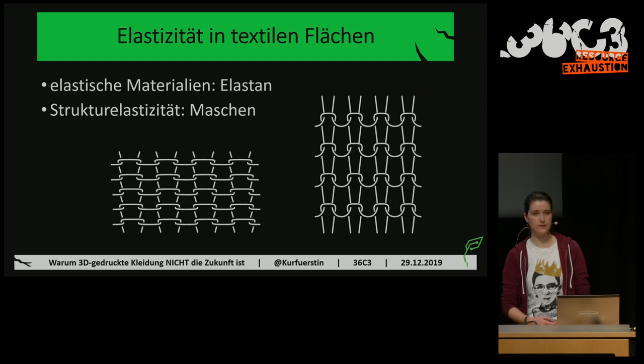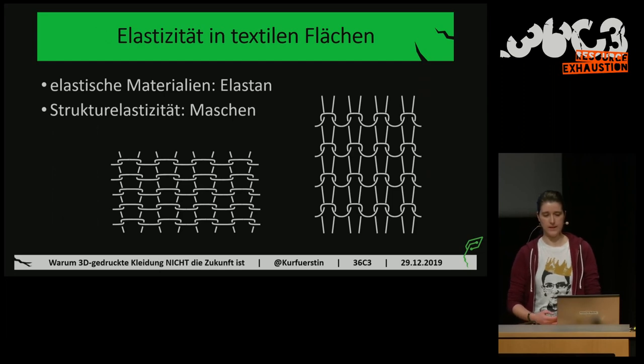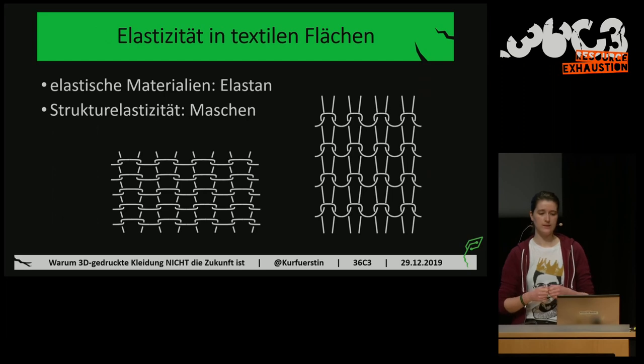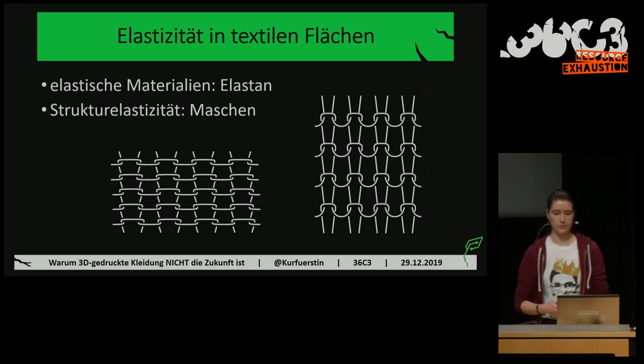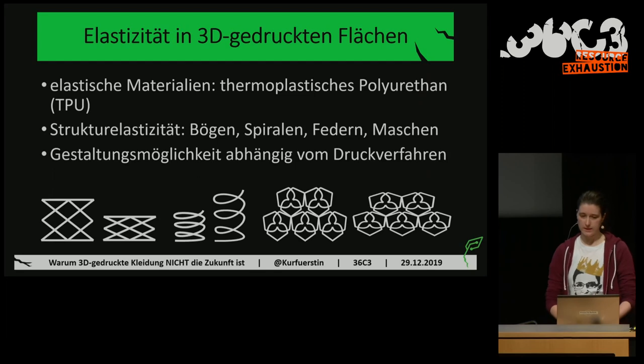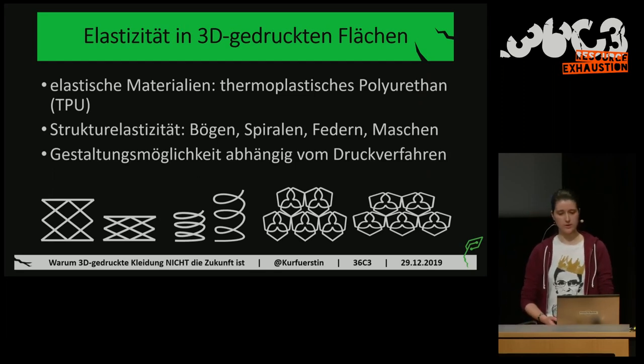The second option is structural elasticity, and that is usually done via weaving. If you pull on a surface, then the threads will move relative to each other and distribute a bit of their thread to their neighbors. And that in combination makes an elastic surface with material that isn't all that elastic. Cotton fiber, for example, isn't elastic at all, but if you weave it the right way, it's a very movable and elastic surface. And if you transfer this to 3D printed surfaces, then you can use an elastic material here,